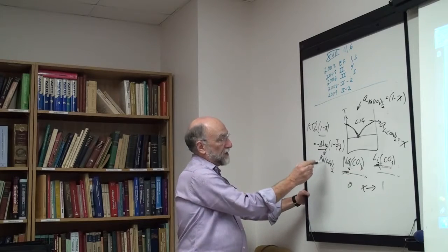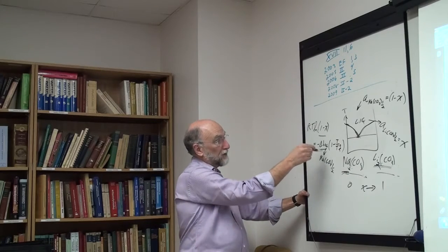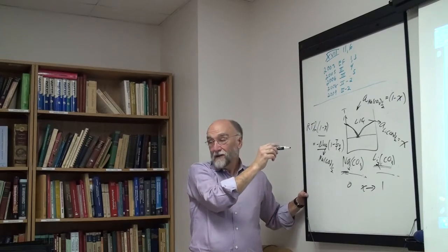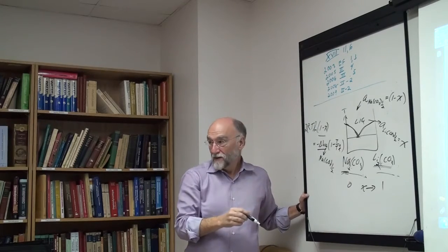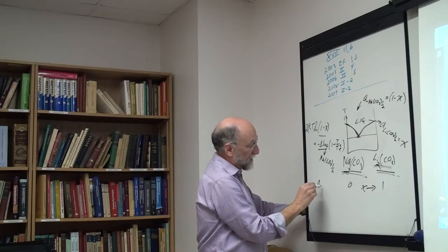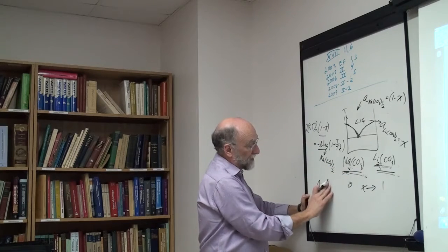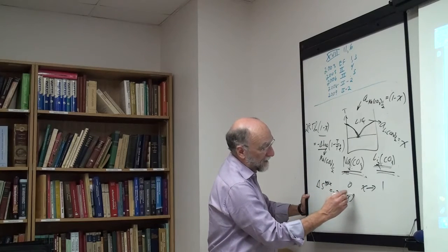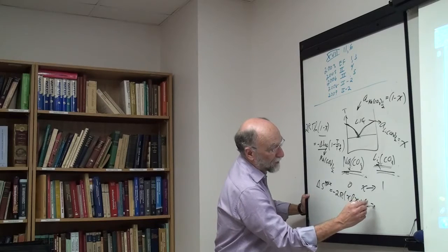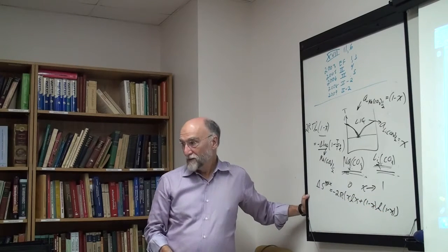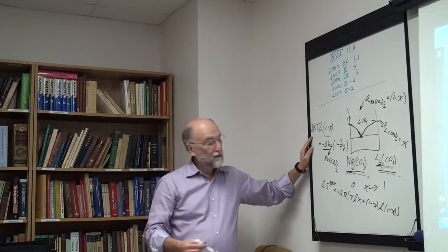In that case, this is the heat of fusion of Na2CO3, which is twice before, so I've got to put a twice over here. So I simply have twice the entropy. In other words, if I'm taking this as my components, the delta S of mixing is minus 2R times x log x plus 1 minus x log 1 minus x. So the 2 would go over here.